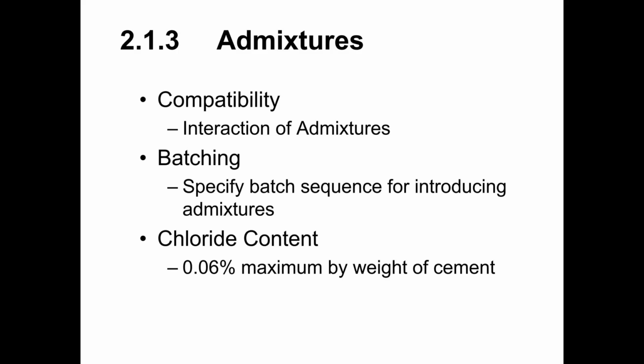Chloride content, we've already touched on this a little bit, but the chloride content for concrete is limited significantly if it is pre-stressed concrete. This will come up again in a later chapter. But because chlorides can be introduced into the concrete through admixtures, it's important that the plant is aware of the chloride content within the different admixtures that they're using, and that they are using admixtures with low or no chloride contents so that they can avoid any potential issues with corrosion.